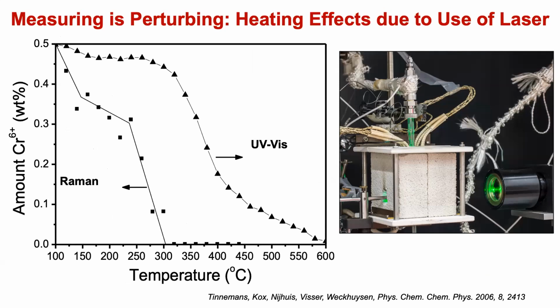I would even say, and now I give you another example. People know that I'm working on propane dehydrogenation. In the first attempts at in situ spectroscopy, published in whatever journal, we measured conversions which are different from what you have in a normal reactor, because the temperature is not right. With an endothermic reaction such as propane dehydrogenation or alkane dehydrogenation, it matters: if you have 40–50% conversion at 550 degrees, and you increase the temperature by another 20 degrees, then you shift the thermodynamics towards higher conversion. Hence, be careful. Double check with the normal reactor.